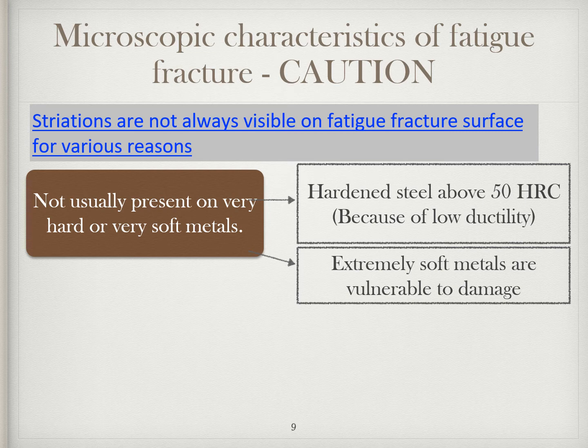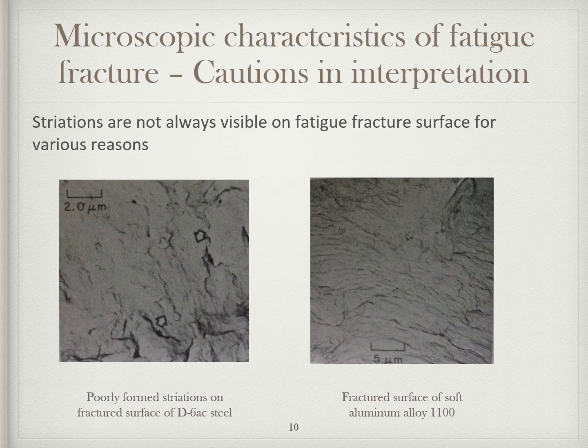At the opposite end of the hardness scale, extremely soft metals and weak metals do not form good striations either, probably because their low strength makes them vulnerable to damage. The figures shown here are the examples of poorly formed striations at the extremes of the strength level. Figure on the left shows poorly formed striations on the fractured surface of D6AC steel. D6AC steel is a vacuum melted medium carbon low alloyed steel and ultra high strength steel. This grade is used for high strength applications like aircraft structures.